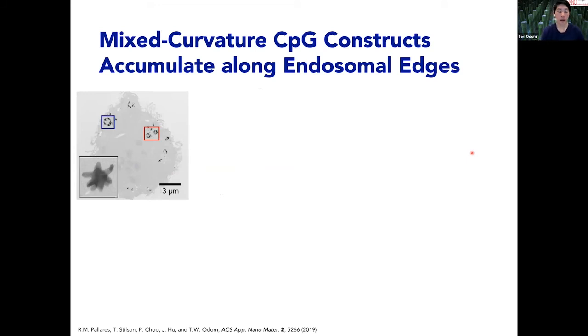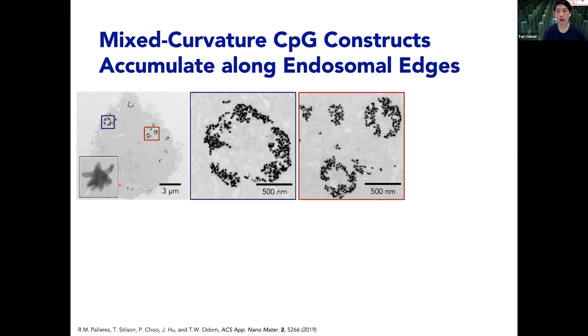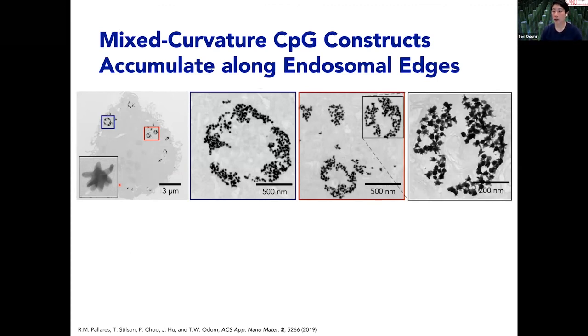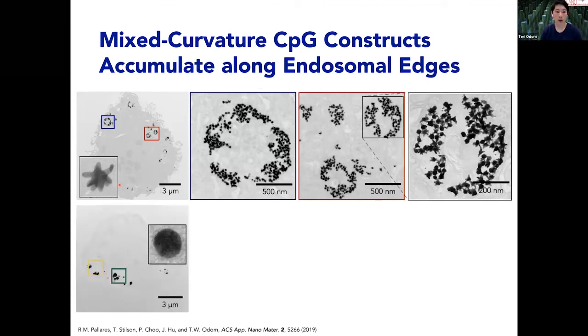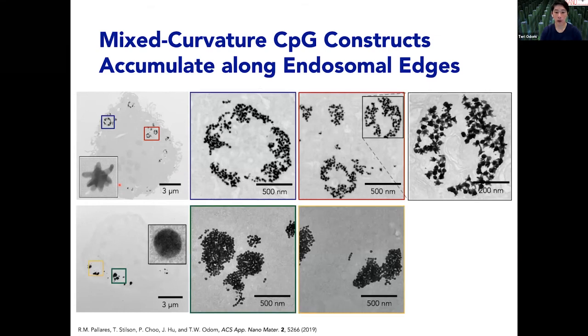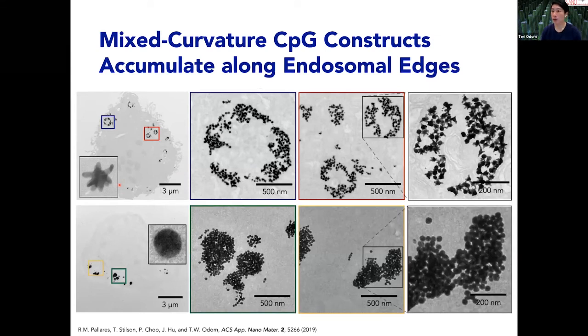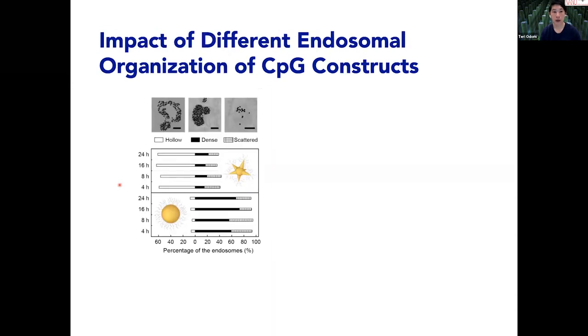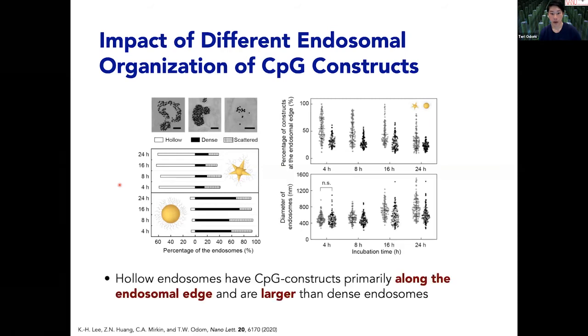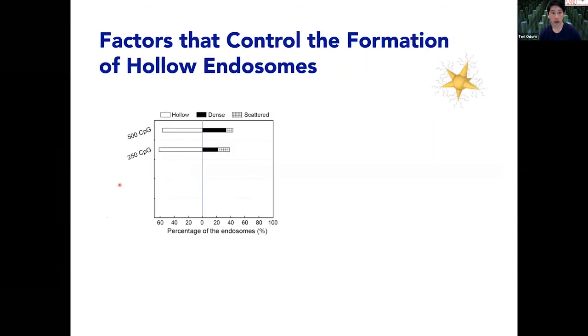And so we found out that if we have these mixed curvature constructs, they tended to organize on the edge of the endosomes. But if you evaluated the effects of spheres, then these mostly accumulated within the middle. So this is quite interesting. These particles, in a comparative way, only have shapes that are different. The amount of CpG is the same. Let me skip this since we're running a little bit behind.